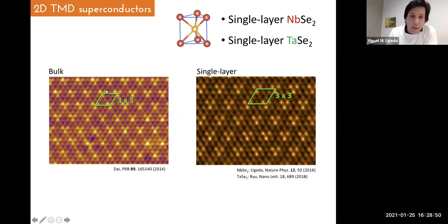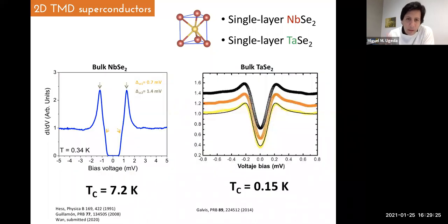They are very similar, and actually both undergo a 3x3 charge density wave order at low temperatures, with different transition temperatures. I think niobium diselenide is 30 Kelvin, tantalum diselenide is around 90 Kelvin, but the periodicity is the same. And actually the STM images, the 3x3 reconstruction, look the same. When you go to a monolayer, this superlattice, this CDW order remains intact in the single layer form in both materials. In terms of superconductivity, these two materials are also conventional superconductors in bulk, although with quite different critical temperatures, 7.2 Kelvin in niobium diselenide and extremely low in tantalum diselenide, 0.15 Kelvin. Okay, there are not many works on bulk tantalum diselenide due to this small critical temperature.